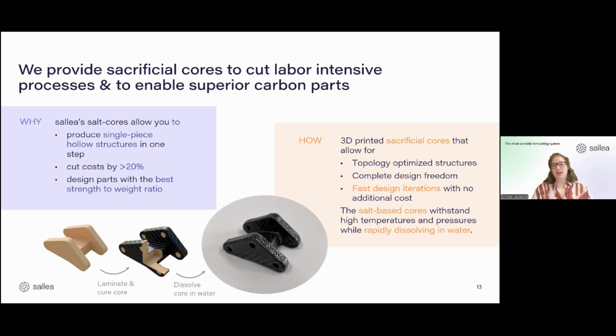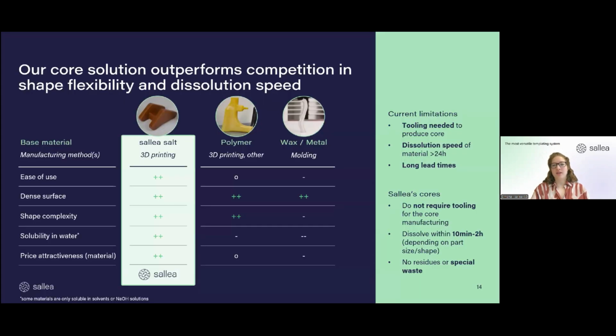Now, I mentioned a bit earlier on that, of course, there are other sacrificial mandrels on the market. And of course, there are way more than I'm showing on this slide, but I tried to group them a bit together. What is quite standard is, on one hand, polymer cores that are often, but not always, 3D printed, and usually also dissolve in water or in an aqua solution, and also wax and metal cores. Going through this list, the ease of use of these cores is often not so easy. For example, for the wax and the metal, I think we saw it before. It's a very tedious process to even get to your core, and that is just very time consuming and a bit of a nasty process.